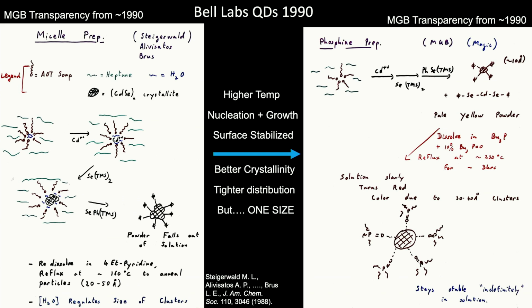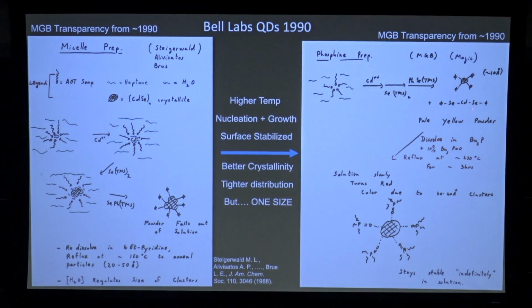So the phosphine that I used, I call that the phosphine prep, was to take what came out of this little powder and redisperse it in this tributyl phosphine, tributyl phosphine oxide, and increase the temperature to 230 degrees. You'll see temperature is important here. Reflux for about 3 hours, and slowly you take really tiny particles here as seeds.